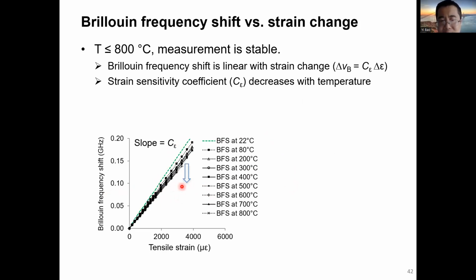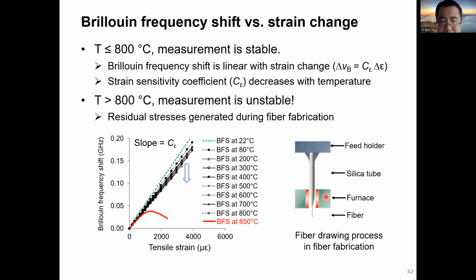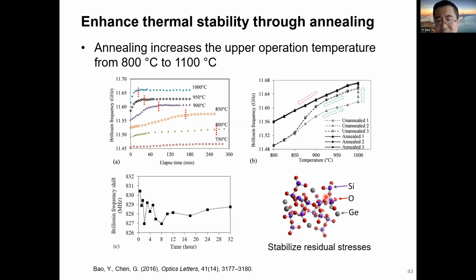However, when the temperature was higher than 850 Celsius degree, the measurements became unstable. So this was because of some kinetics of the residual stress within the fiber optic sensor. The residual stress was generated during the glass fiber fabrication process, and at high temperature, the residual stress would be released and therefore affect the microstructure of the glass fiber.